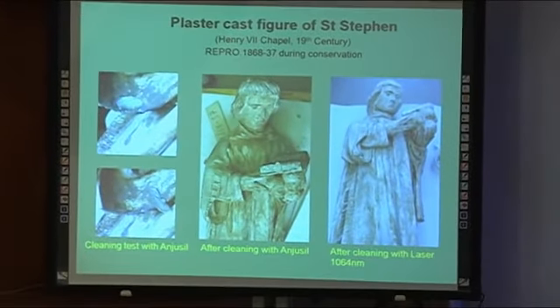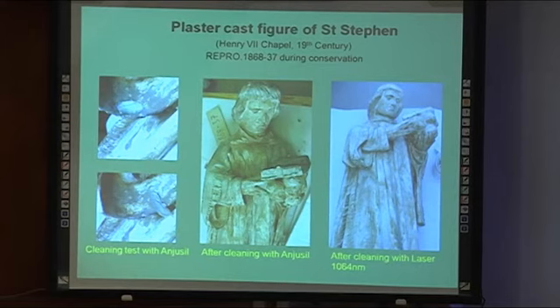They also did not chemically react with any treatments applied. Neither were they abrasive as dry cleaning methods or solvent swabbing. Most importantly, they contain a negligible amount of water. The Nd:YAG laser cleaning showed the least alteration to surface roughness, but on test samples there was a slight color change. In a separate investigation on an aged plaster cast at City and Guilds of London Art School, the laser successfully removed surface dirt used at a fluence of 0.15 joules per centimeter squared at a wavelength of 1064 nanometers.